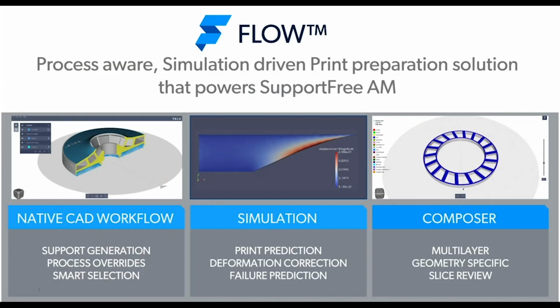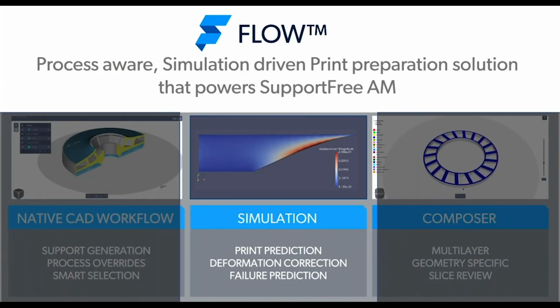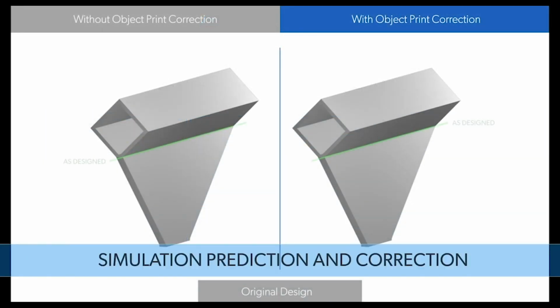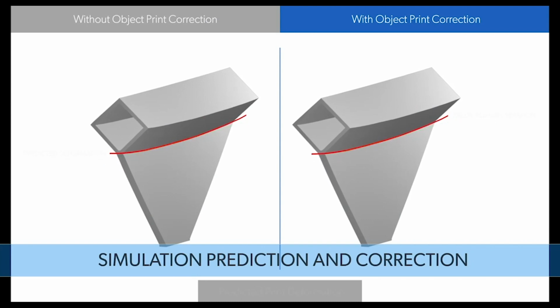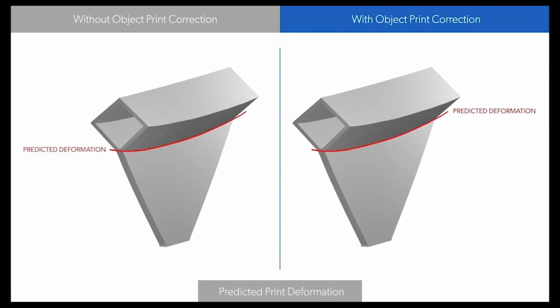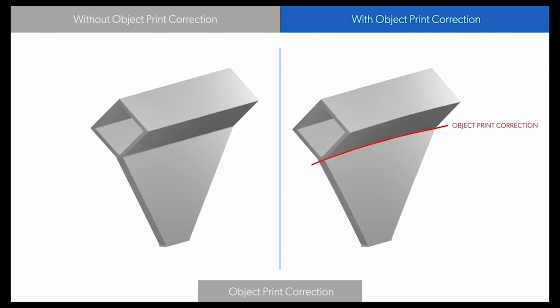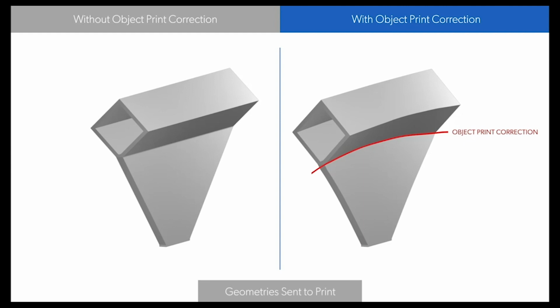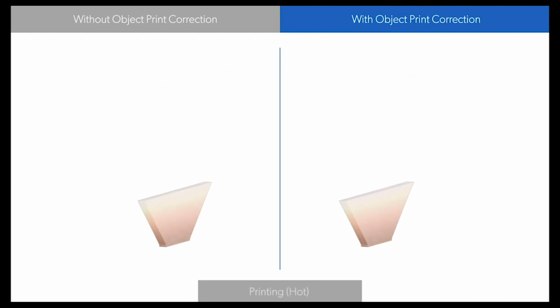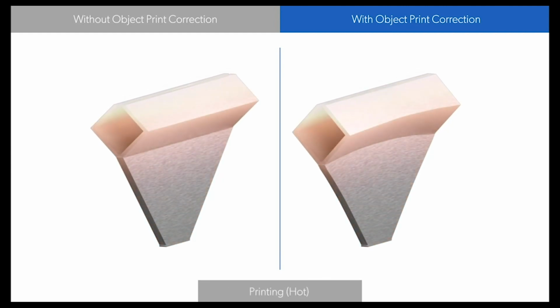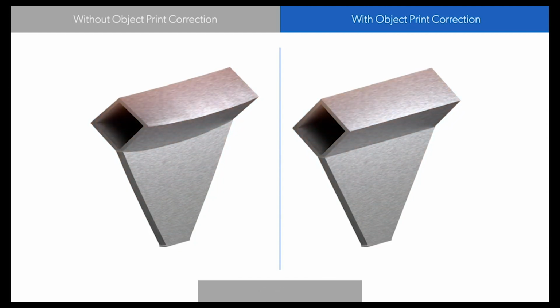An example video is being shown here of exactly how that happens. So in this case, it's focusing on this very simple test structure, which is just shown to sort of give an idea as to how it works. So as printed, any sort of horizontal bar that's printed on the laser powder bed system will have a tendency after it's cut off the build plate to warp up into a smiley face structure. What this does is that it pre-simulates that deformation that's going to happen, and it distorts the geometry down such that after the part is finished printing, it's warped up now to the proper shape.